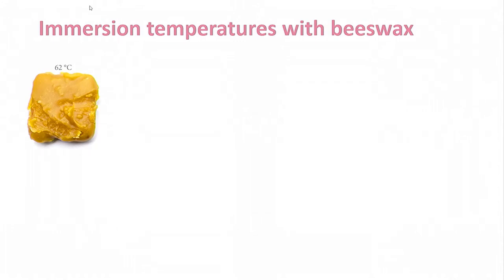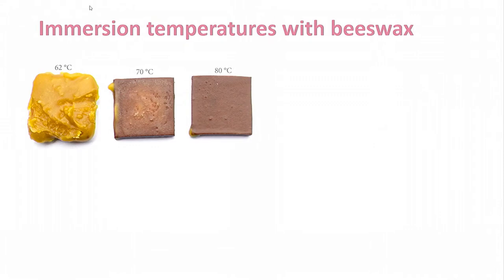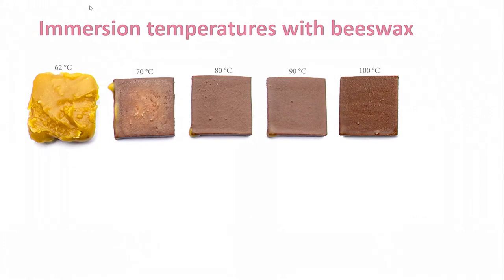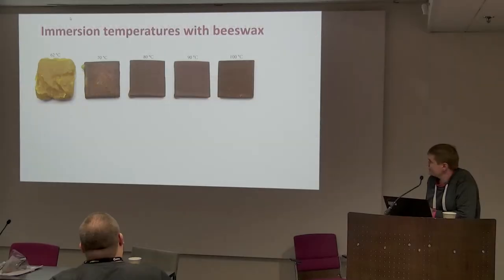So 62, 63 is the melting point of beeswax. This is what you get if you try to have 62 degree beeswax and leather in it. This is 70 degrees, 80 degrees, at this point 90 degrees, 100 degrees. At this point, you can see that there is no extra wax that has been built on top of the leather. So around 100 degrees is the lowest I would go with beeswax when hardening leather. But then again, I wouldn't use beeswax.